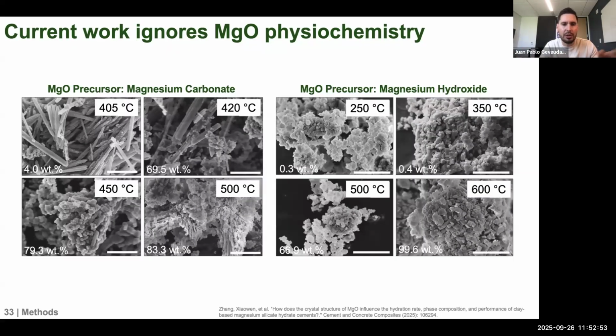And for magnesium carbonate, what you can see here on the left is that the percentage of magnesia increases, in white on the lower left-hand corner here. But you can see that magnesia nucleates on the surface as little globule nuclei that eventually cover the needle-like morphology of this hydrous magnesium carbonate. However, very interestingly enough, brucite retains its structure. It doesn't really change much, even though it's converting to magnesium oxide.